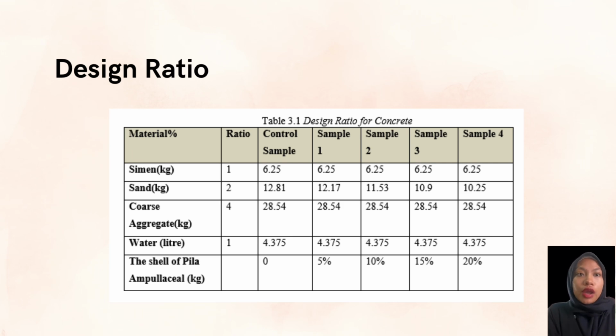So we have four samples here, excluding the control sample. Control sample we use 0 percent of the shell. For sample 1 we use 5%. For sample 2 we use 10%, and for sample 3 we use 15%, and for sample 4 we use 20%. So the change of the ratio is, we can see it's the same. So the sand will be less because we substitute or replace the sand in the concrete with the percentage of Pila Ampullacea.